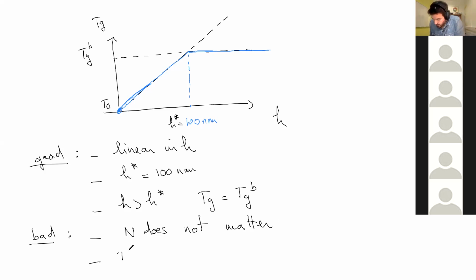Secondly, it seems that TG is always bigger or equal to T naught. When the sample size goes to 0, the minimum value is T naught. And again, this is wrong experimentally. There are observations below T naught. So the model doesn't capture those fine details. Okay. So just to summarize, in the confined glasses community, which is a restriction of the glass transition community, there is this first mechanism that allows to explain some features of the reality, but not others, and it's still an open problem. So people are working on that and trying to understand it.